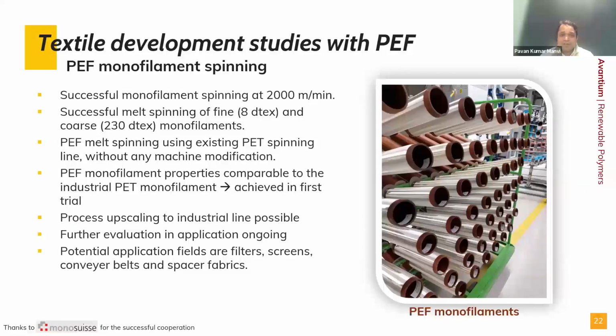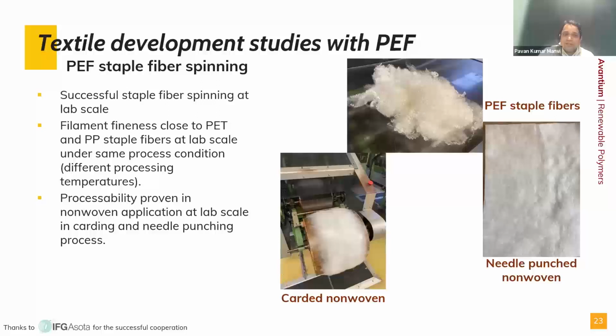We did a similar thing with monofilament also. We have done the monofilament melt spinning process development, which was very successful. Upscaling and optimization are ongoing, and we are looking for a range of applications based on the monofilaments. There were trials to develop PEF based staple fibers, and you can see that we have successfully made crimped staple fibers. Then at the lab scale, we have proven the non-woven possibilities based on PEF fibers, and by needle punching, we have made successful non-woven fabric.